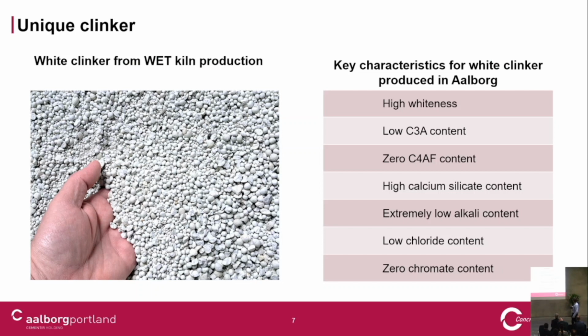And what are the key properties of this clinker? Because of our process, high whiteness, because of the uniformity in size we can have more control of the heating, the temperature profile through the clinker, and also the cooling of the clinker is important - we capture the high temperature phases and quench very quickly. And also the oxidation that is happening on the clinker - the iron is locked in a state where it has no color, a very small amount of iron that's in there.